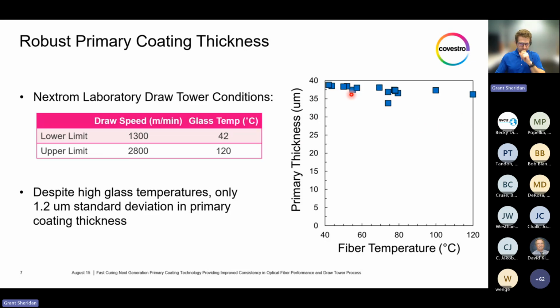As we can see, there's about a 5-micron decrease over the entire range from 40 to 120 degrees Celsius, with about 1.2 micron standard deviation in primary coating thickness. We believe this demonstrates the robustness of this next generation primary technology, lending to only a 1.2 standard deviation or a 5-micron decrease over a wide range of fiber temperatures all the way up to 120 degrees Celsius.